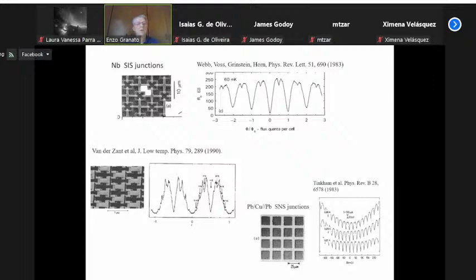Now I will show some of these experimental systems which can be modeled by this superconducting array. On the top left is one of the early arrays, made of superconductor-insulator-superconductor (SIS) junctions. You see the resistance as a function of frustration, which is the magnetic flux per plaquette divided by the quantum flux, with a minimum at the integer values and a secondary minimum at 1/2. There's another one in which you can see higher order minima at the higher order commensurate states, besides the commensurate states at the integers.